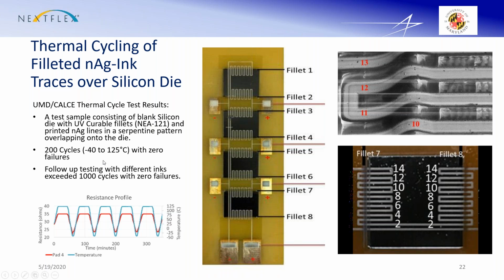And we chose -40 to 125. That's one of our typical profiles for military use for qualification. And I'm not saying that we didn't have a few false starts with getting this and some lessons learned. But at the end of the day, when we felt we had things under control, we printed a nice print. We were getting 1,000 cycles with no failures, -40 to 125. So we were really pleased with that. And we learned a lot of stuff along the way.